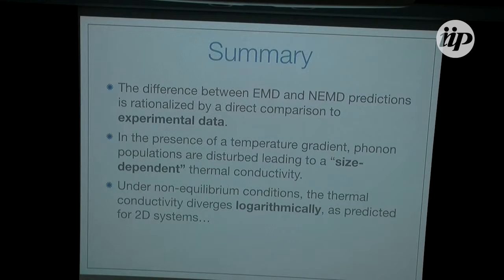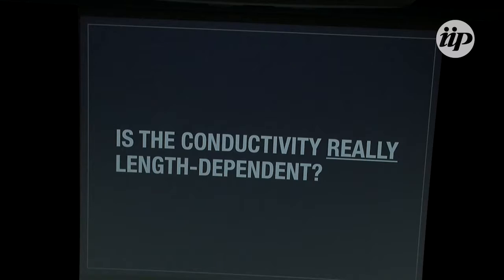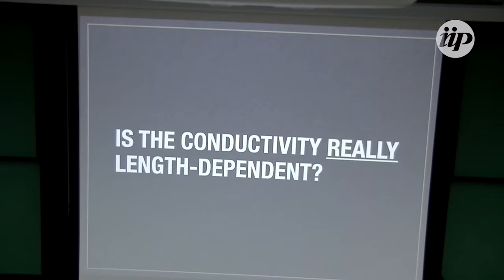So when we compared our EMD and NEMD results to the experimental data, we realized which one of them was right. Now we find this size-dependent thermal conductivity, and we see that it diverges logarithmically with the system size, as predicted for an ideal two-dimensional system. Now,